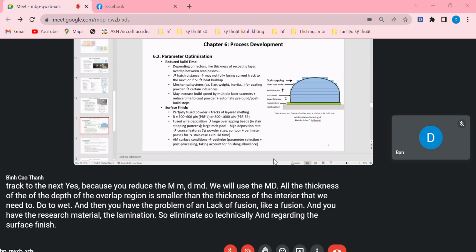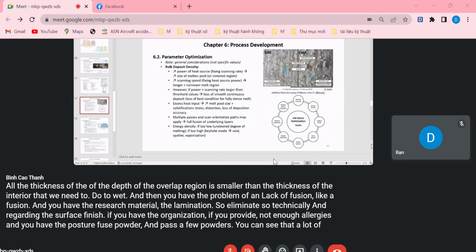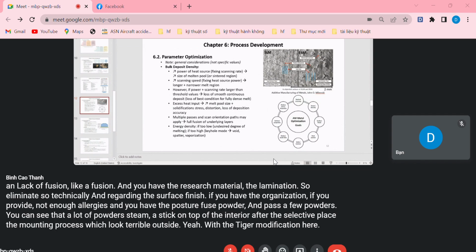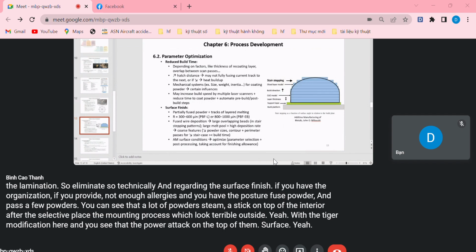And regarding surface finish, if you provide not enough energy and you have partially fused powder, you can see that a lot of powder still sticks on top of the material after the selective laser melting process, which looks terrible, I would say. With high magnification here, you see that the powder attaches on the top of the surface.